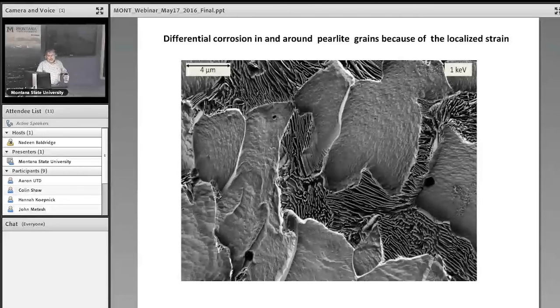Like a bomb exploded there. Now you can see this is a pearlite feature here. Every iron in between the two layers, lamellae, I think, is eroded away, because this was initially a very solid material. This is a carbide, and next to it, what looks like a hole used to be iron. And strain: iron likes to choose freedom, to wander in the solution as an iron ion rather than stay strained. Even if it's not living, freedom is what it chooses. Minimum gives free energy. So strain means corrosion, and that's universal. We discovered this actually, we just sent it for publication.